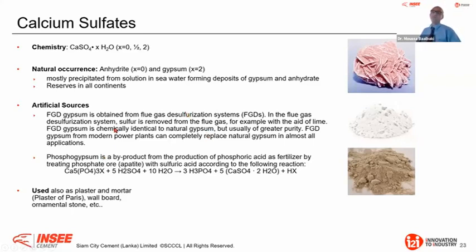Also, we have what we call phosphogypsum. This is a byproduct from the fertilizer industry, where for the production of phosphoric acid as a fertilizer, we treat phosphate ore with sulfuric acid. Therefore, we produce phosphogypsum; I will not discuss the reaction here. The main challenge here, and at INSEE we look very much at that, is that very often they have some radioactive elements. I'm not saying all of them do, but it's very important that we look after this issue that phosphogypsum can bring to the use of this type of gypsum in cement production.